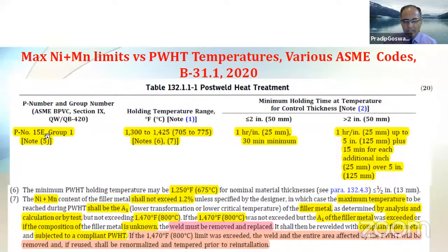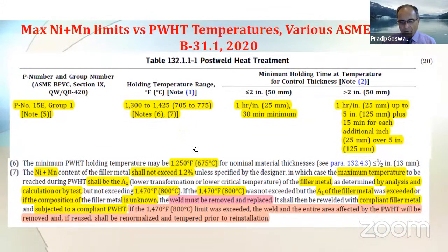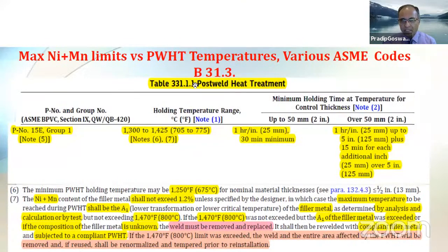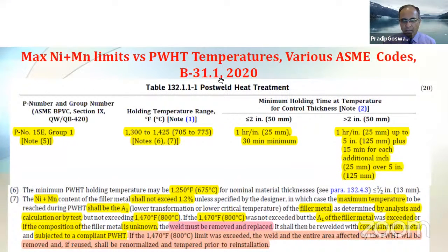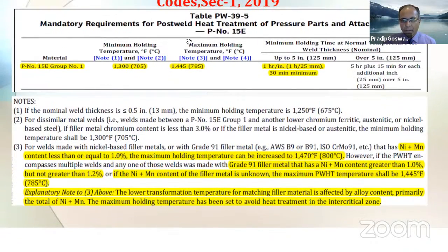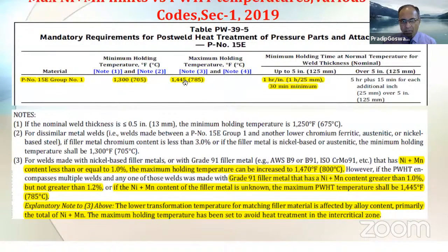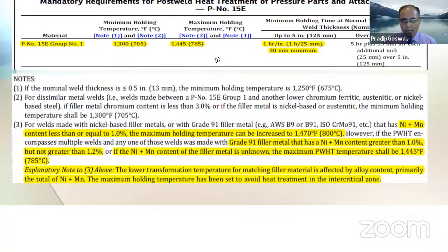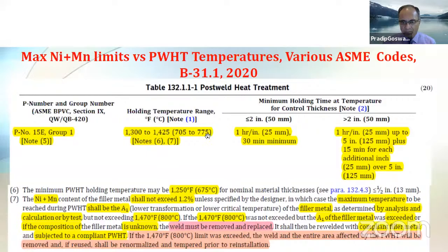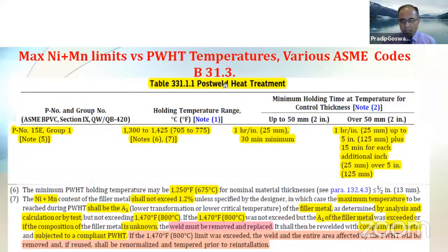Now, as you see here, these alloys are classified as P15E group 1 with respect to ASME Section 9. And the nominal post-weld heat treatment temperature recommended by the code is 705 to 775 degrees centigrade. As you see here, there is a very wide allowance. Sorry, this is for B31.1. And when you go to Section 1, the boiler code, it is 705 to 785. And for B31.1, it is 705 to 775. B31.3 piping code, for the process piping, it is 705 to 775 degrees centigrade.